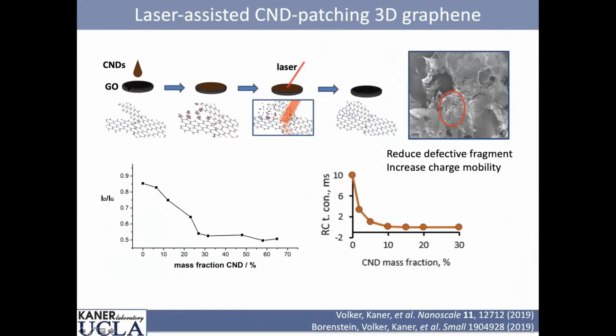We take our graphite oxide, we put our carbon nanodots, we hit it with a laser, and if you look under a microscope, you'll see this. Here's the graphene produced from graphite oxide. There are the carbon nanodots. And it actually lowers the amount of defects. We can see this in the Raman. This is the D to G peak. G is the graphitic peak. D is often considered the disorder peak. As we put more of these carbon nanodots, we actually improve the graphene, and we've run the time constant down. As I said, we're down below 1 millisecond. This is work done by Ari Borenstein, who's now a professor at Ariel University.